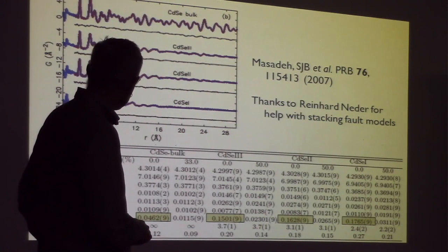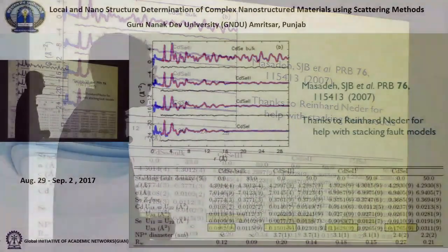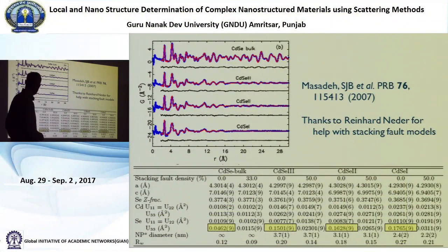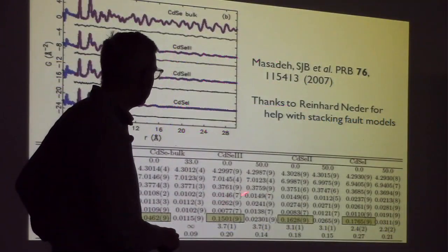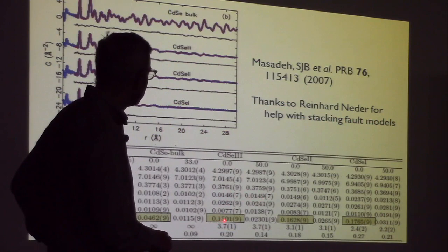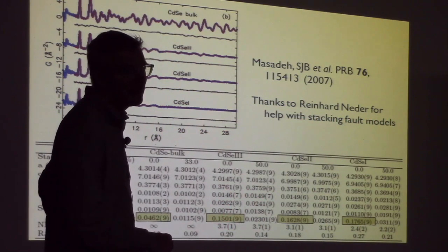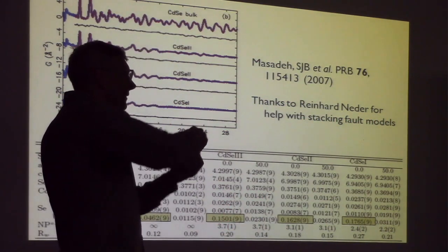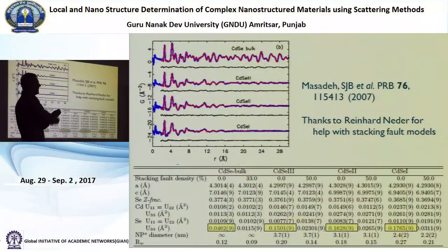And we can put in an anisotropic ADP, atomic displacement parameter, and we can allow this U33 to change. And what we find is that the values for these U parameters should be like this, 0.01, 0.02. These numbers are okay. 0.15, this is 10 times too large. It kind of implies that atom is executing a thermal motion which is 10 times normal. This is completely unphysical. It's completely wrong.